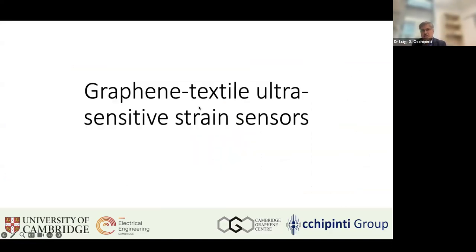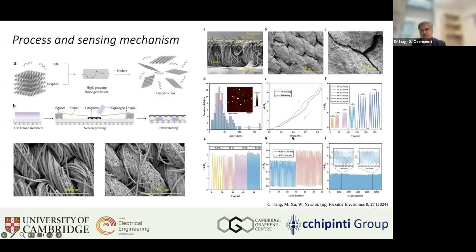Another area is, again, on graphene textile sensors. We also use a similar process to coat textile to act as strain sensors. We discovered that the mechanism behind the strain sensing in graphene coated textiles can be related to microcracks and the formation of ordered microcracks in the textile structure that actually determine a reversible approach for strain sensing with a relatively high sensitivity, higher than other techniques, for instance, based on piezoelectric materials. Also the process is relatively simple.